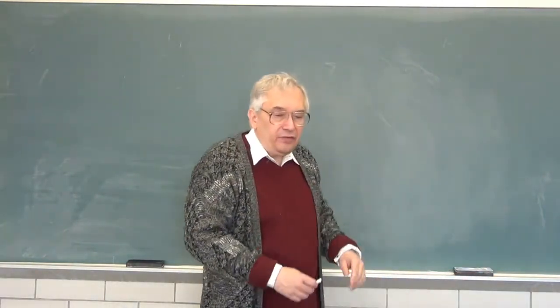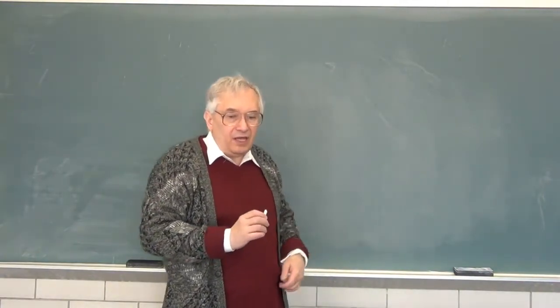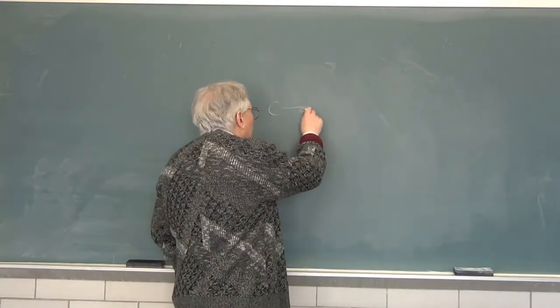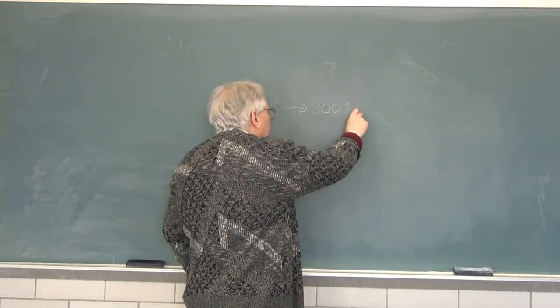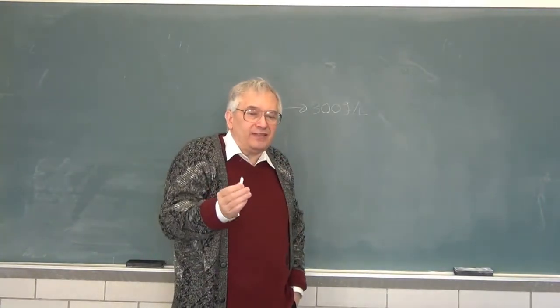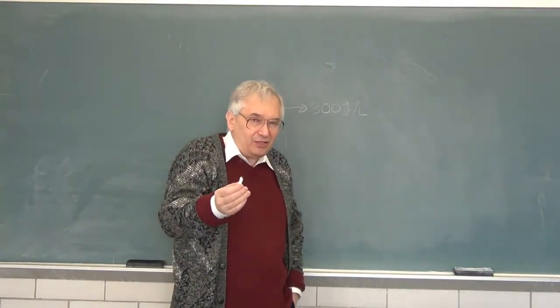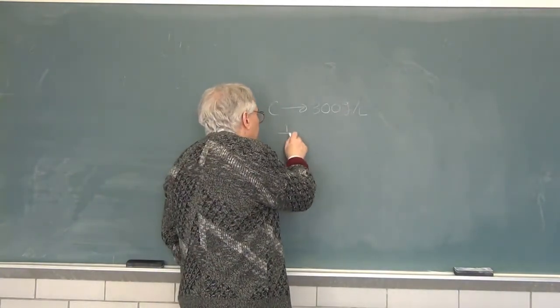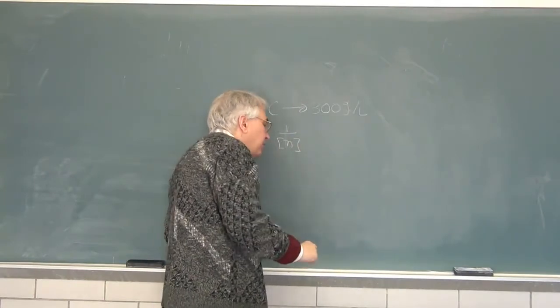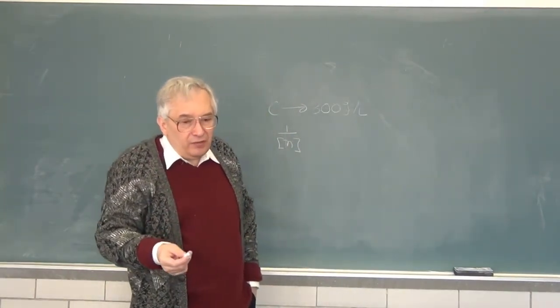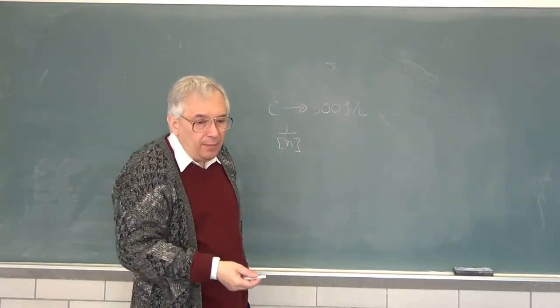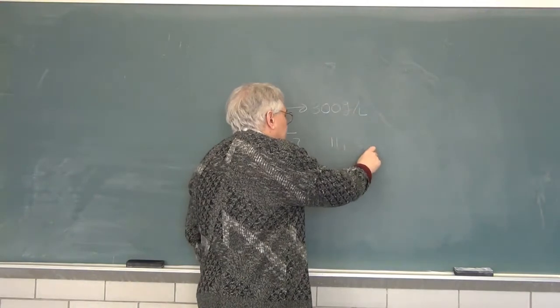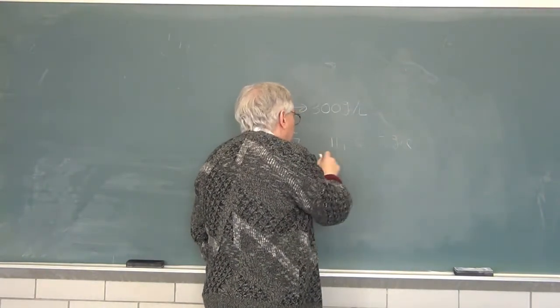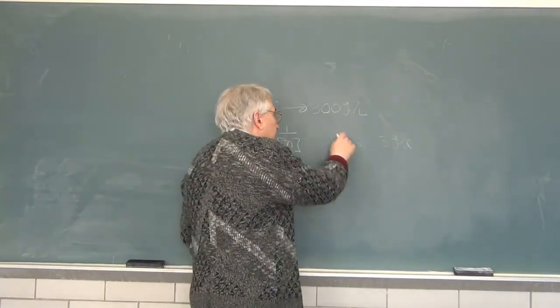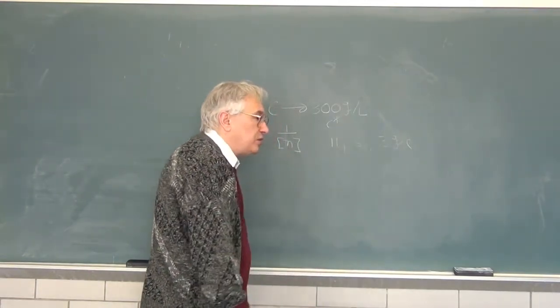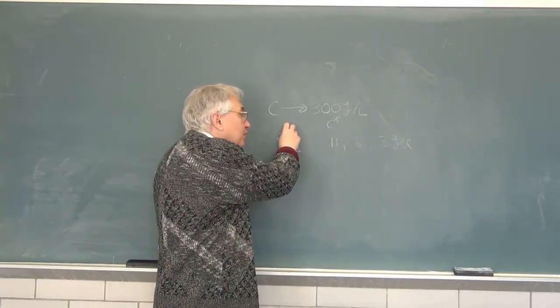In particular, if you go through the full series of papers, you find that they took the concentration out to 300 gram per liter of polymer. They also did viscosity measurements. We'll talk about viscosity more later in the course, but the core answer was that the intrinsic viscosity, or rather its inverse, was for these three materials, 11, 6, or 3 gram per liter. Eta intrinsic is in liters per gram, of course. And these are overlap concentrations, C star. You can have different numbers up here, and different authors do that.